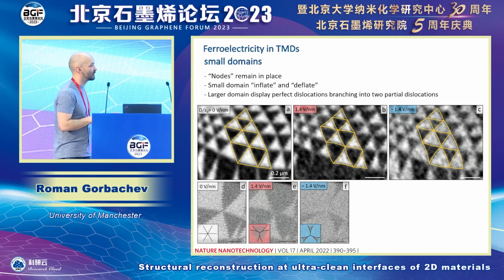You can see that small domains, for example, they sort of inflate and deflate, but the junctions, these middle points, they don't move because there are three domains on each side of that point, and the forces are compensated from three sides. So these nodes, they don't actually move when you start to switch these devices. And this is quite critical, for example, if you want to make an applied ferroelectric junction out of this material.